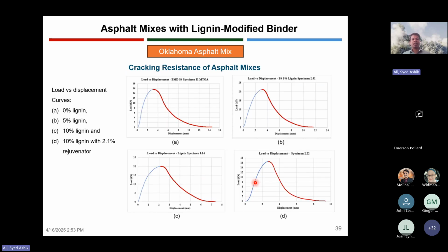Cracking resistance. So what we have seen on the cracking resistance: we took 4 different samples. This is the load displacement curve for cracking resistance. The first one is for 0% lignin, the control mix. Then B is for 5% lignin, C is for 10% lignin, and D is for 10% lignin with 2.1% rejuvenator. What happened with the addition of lignin is that the ultimate load to failure increased significantly.